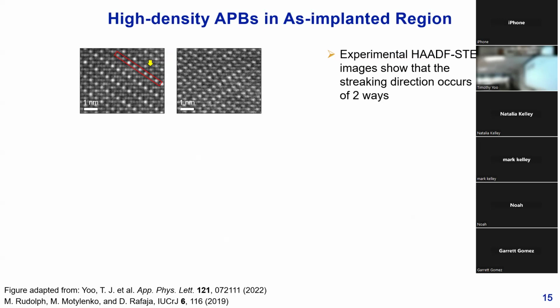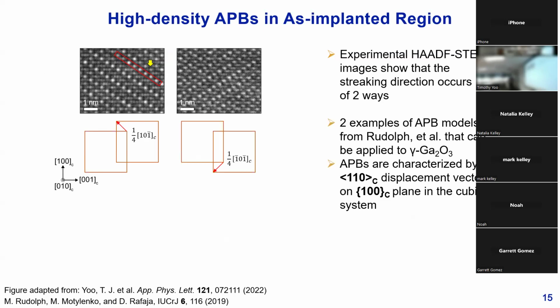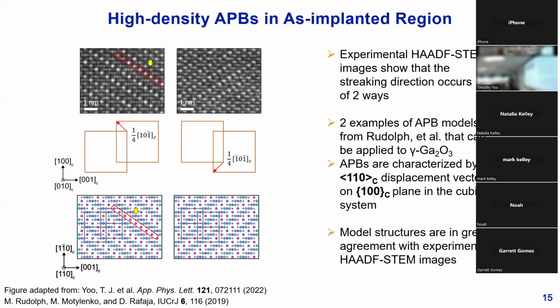And so here we have 2 snippets of STEM images with streaking directions of 2 different types. If we apply an anti-phase boundary model that's been proposed by Rudolph and colleagues a few years ago on gamma aluminum oxide, which has the same space group as gamma gallium oxide, we see that this anti-phase boundary model applied to model structures has really good agreement with our experimental images and with these streaking individual columns and these triplets, giving us good confidence that what we're seeing here is indeed due to a high density of anti-phase boundaries.